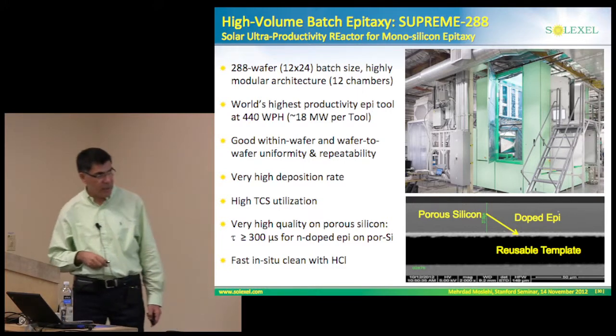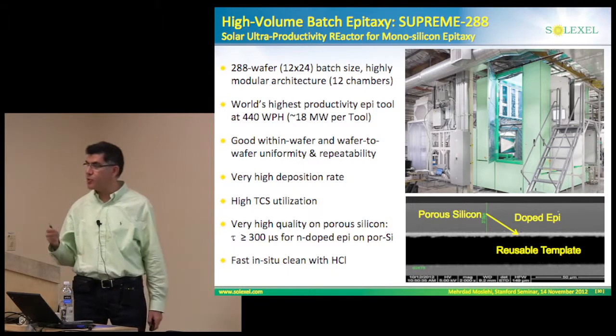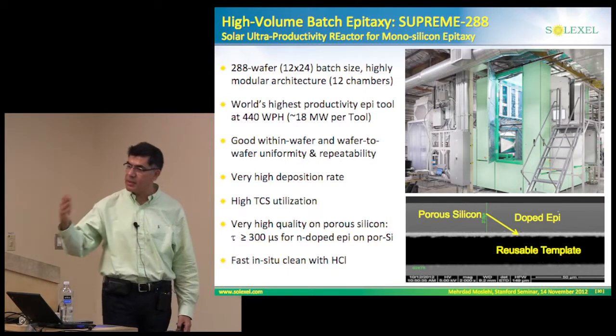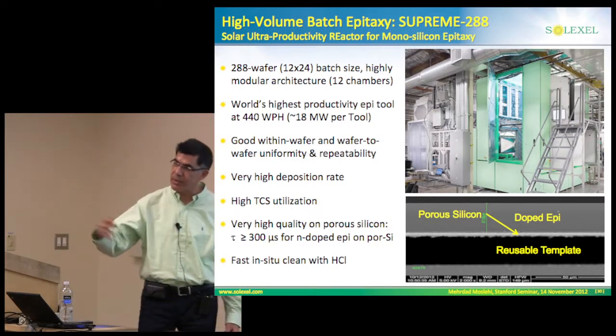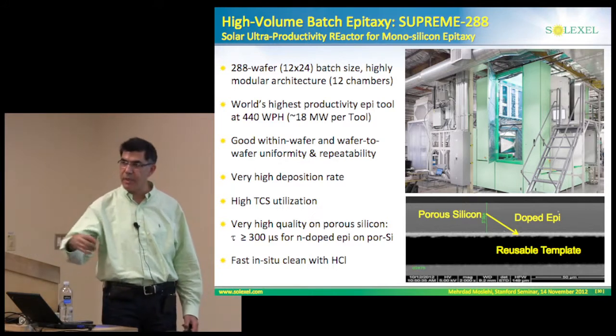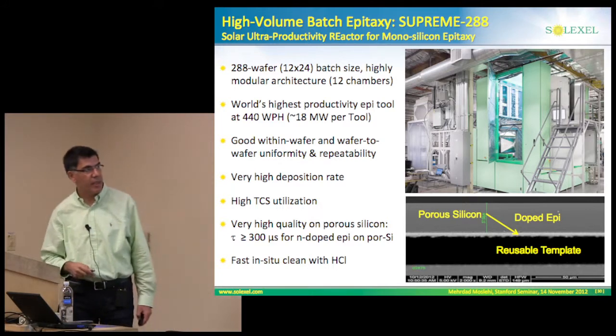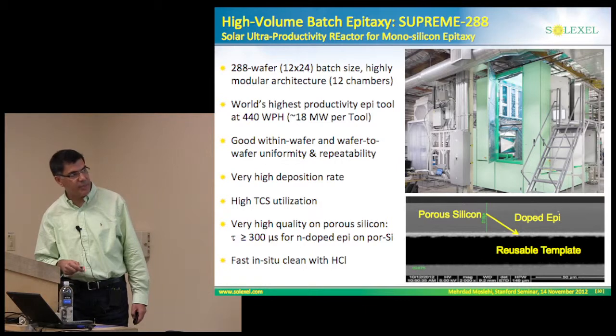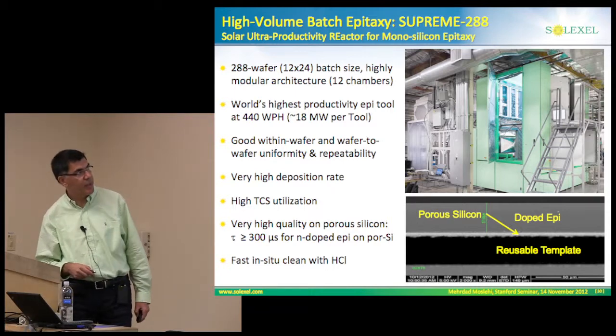And the tool provides in situ clean with HCl. So every 10 to 14 runs, we do one in situ clean with HCl in the tool. This is an example of a cross-sectional profile that shows our template. This is a porous silicon, and this is our doped epi.